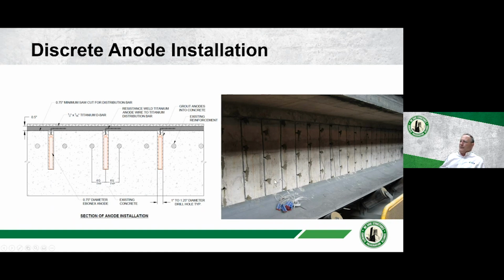In this case, you can see the anodes are placed, and they did it in a staggered fashion on this wall. The reason they did it here was chloride contamination in the mixed water to begin with. I don't know if it was the mixed water or the sand. I think it was chloride-contaminated sand, and so they had to put impressed current in this relatively new structure.